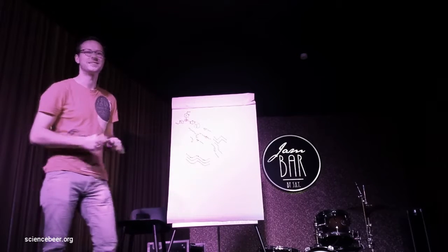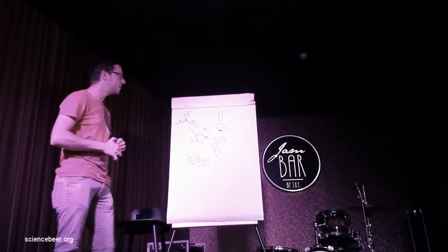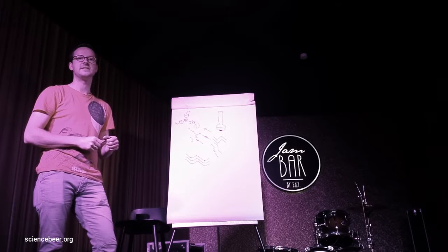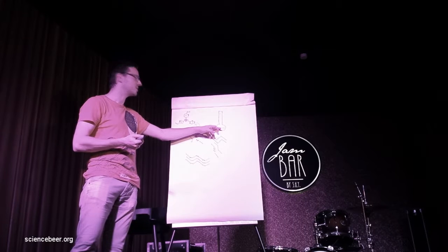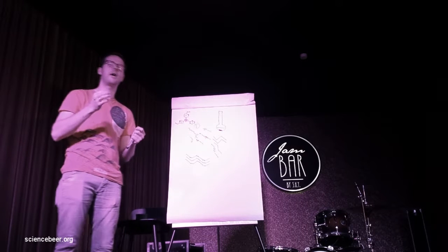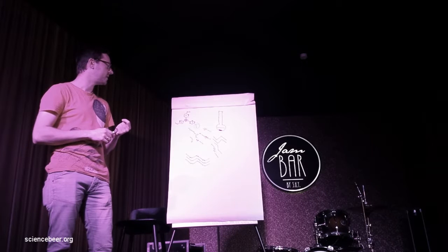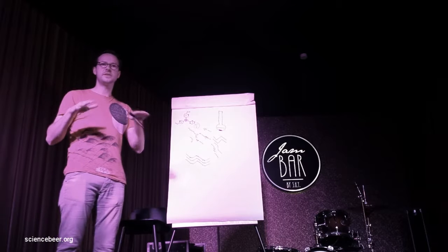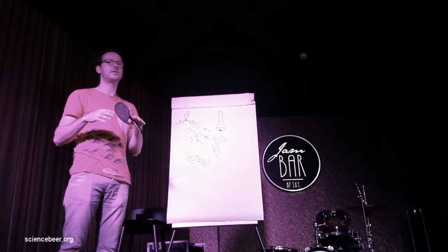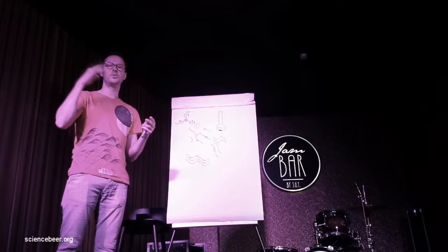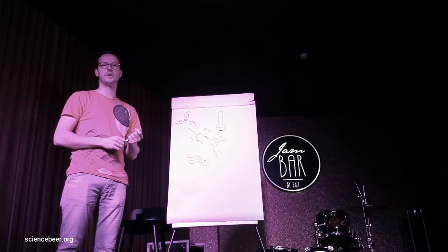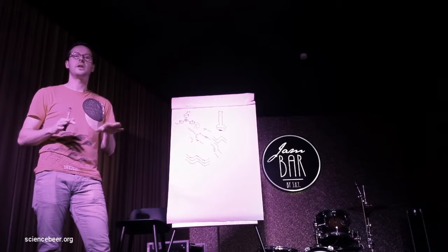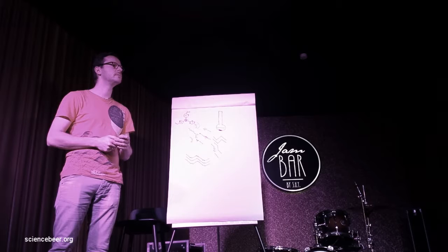How do I synthesize this actually? I just use an ampule under vacuum, so I evacuate it, I close it, and then I put it for several days in the oven. I use a solvent which is very bad for these molecules. Only a small part of the molecules is dissolved and reacts in the solution. Inside it reacts one after another. So at first it's dissolved in the solvent, but at some point when the polymer grows too big, it will precipitate, but then it will go on growing one on another. When we have some oligomers, then it will precipitate very early and react in the solid. So basically you don't know what you are doing.